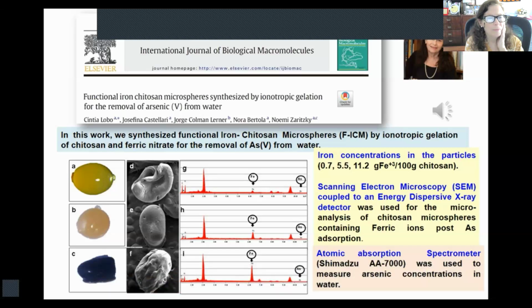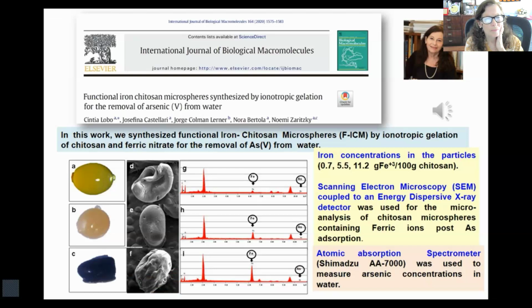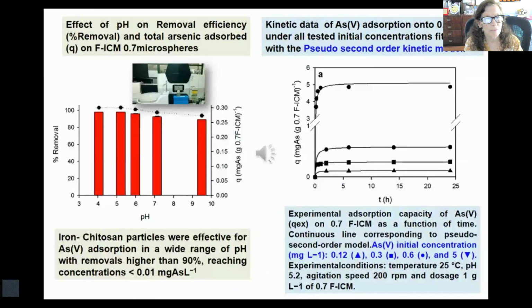We used different iron concentrations in the particles, and scanning electron microscopy coupled to an energy dispersive X-ray detector was used for the microanalysis of the spheres. Atomic absorption spectrometer was used to measure arsenic concentration in water. Iron chitosan particles were effective for arsenic adsorption in a wide range of pH, with removals higher than 90%. Kinetic data of arsenic adsorption under all tested initial concentrations fitted well with the pseudo second-order kinetic model.